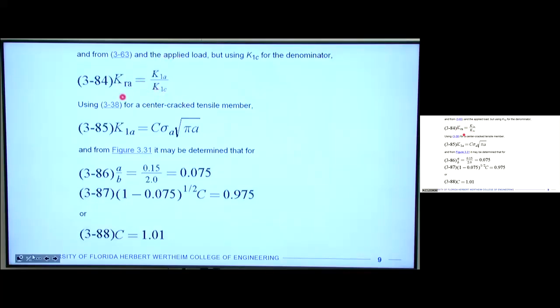For a center crack tensile member, this is the equation for the fracture toughness. If we wanted to include everything in the strip model, we could include that other term off to the side, but for simplification we're just going to use the K1C type equation. So we have a geometric factor C, our applied stress, and the square root of pi times the crack length A. A over B is half the crack length divided by half the width of the bar. The crack length was 0.3, so 0.15, and 4 inches divided by 2 is 2. So this ratio of A over B was 0.075.